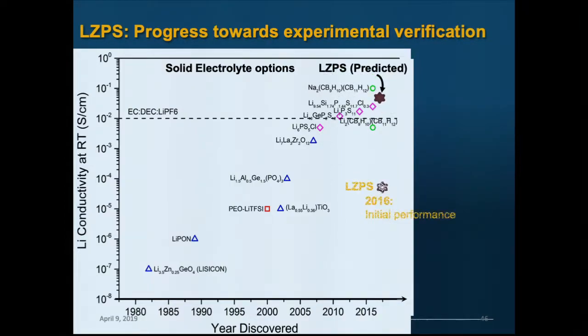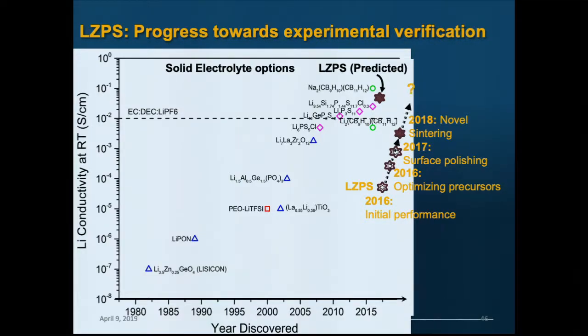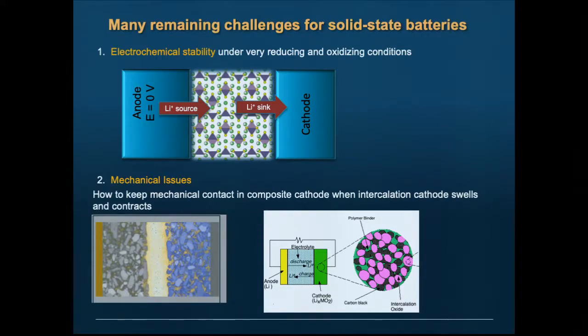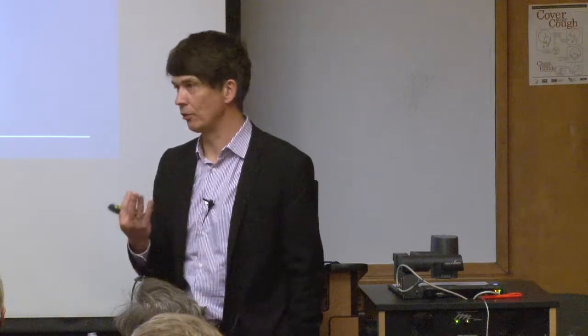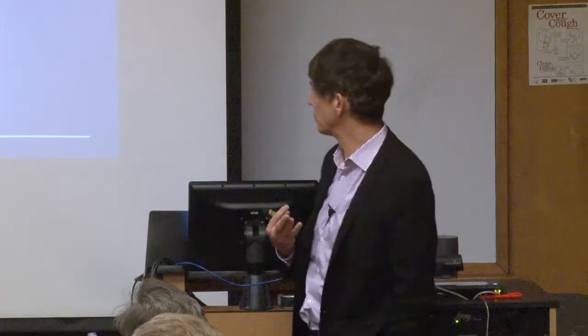We have been able to get reasonably close over many years by working with our collaborators at Samsung by improving processing methods. And we are essentially now within an order of magnitude of the target. That may seem like terrible, but in the world of ionic conductors, an order of magnitude is not a lot in terms of milli-electron volts. So by now, it is among the best conductors, but it is not nearly as good yet as we predicted. Okay. So I think we start to know fairly well how to make good conductors. And I think what we're learning is that there are probably many more good conductors for ions than we actually thought there were. That this is actually not as unusual as we thought.